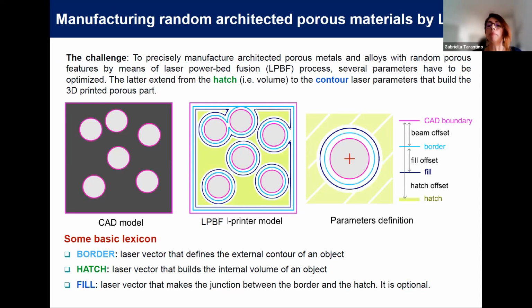Now, when it comes to metallic 3D printing, and that I can say by experience, unlike polymer 3D printing, we have a wealth of process parameters which we must take into account. The former are the conventional parameters which we all know in laser powder bed fusion additive manufacturing, basically how we construct the volume. But the peculiarity of this material is that they contain particles which are embedded into the matrix. And as you can see from the sketch here, the majority of the volume of this part is built using the contour parameters.